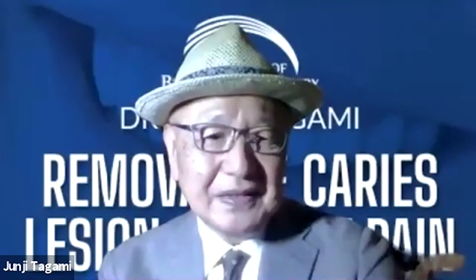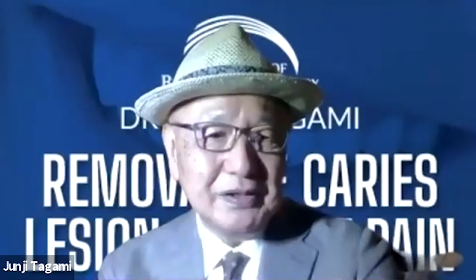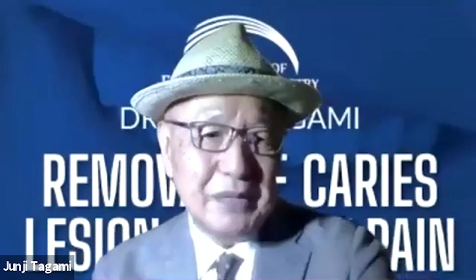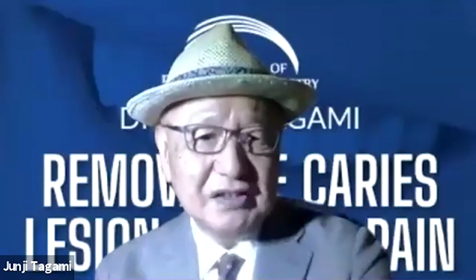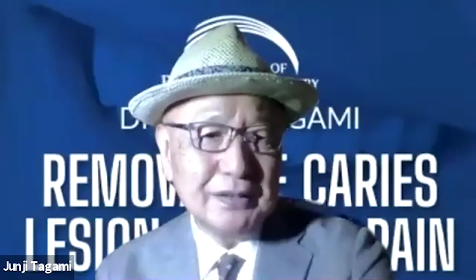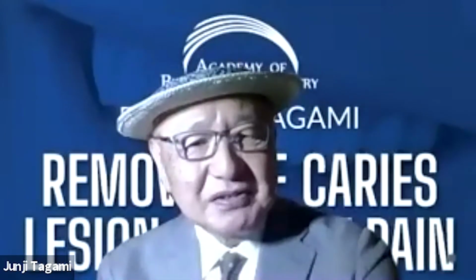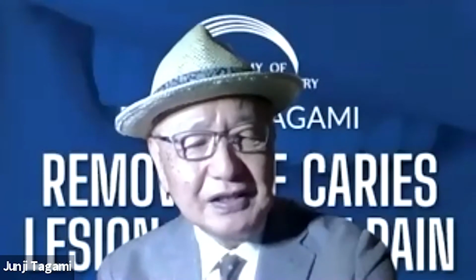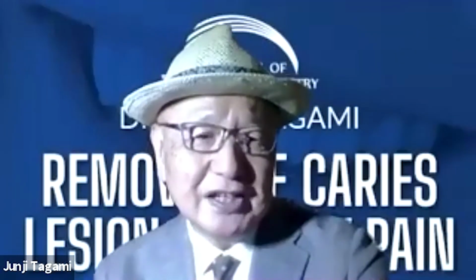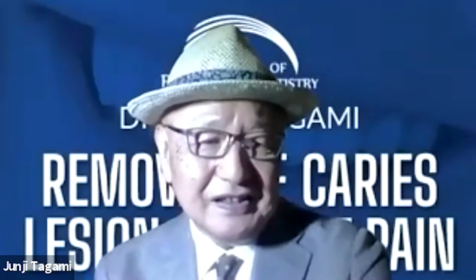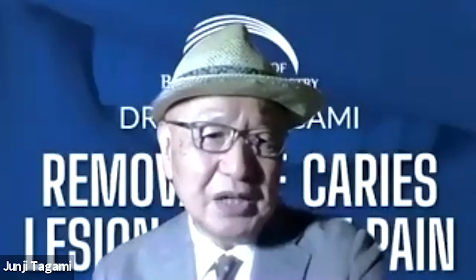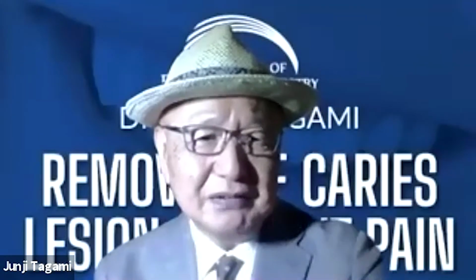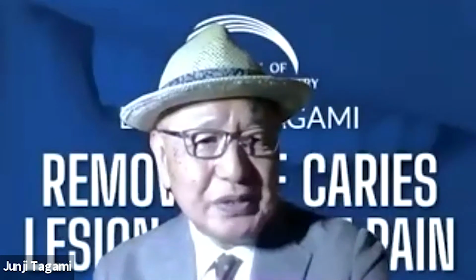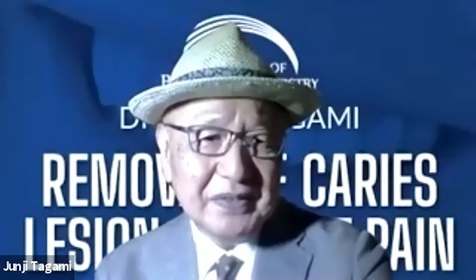But after that, we could develop another kind of testing method, like the micro-tensile testing method or micro-shear testing method. Then we could differentiate the performance of the new materials again. And also afterwards, there was the traditional research regarding the performance of bonding from the viewpoint of the gap formation in the cavity. And when we had the new OCT machine to analyze the gap formation without any invasive approach, we could see a lot of new findings.